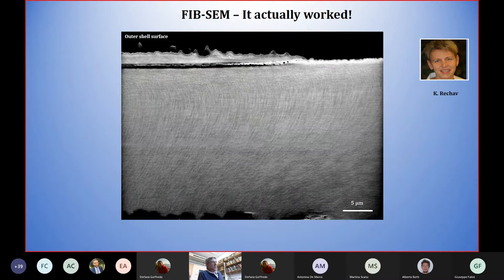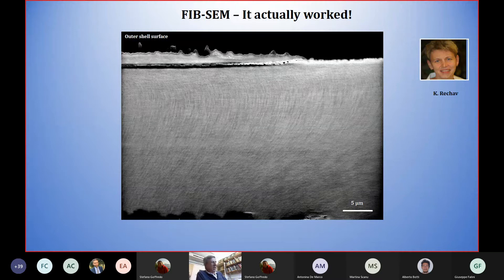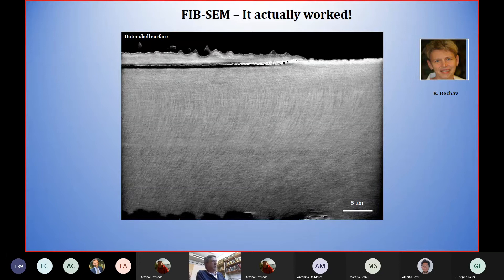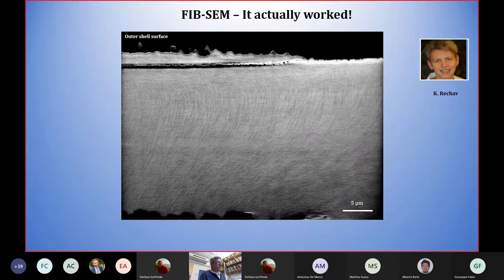The trouble was that pteropod shells have less than 0.01% organic matter, so we had no idea where the contrast would come from. But the first image we got when we put a pteropod shell into the FIB-SEM amazed us — without doing anything to the shell, we could clearly see the outlines of the curved arrays of aragonite crystals. The quality was poor compared to what we were used to, but we knew we could only improve it from there.